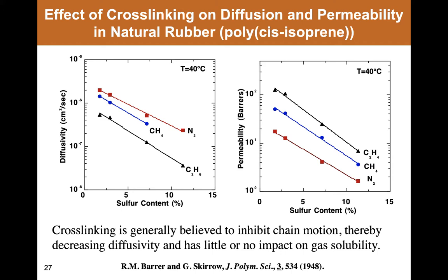And so what's being shown in this slide is the permeability of natural rubber as a function of the sulfur content. And as the sulfur content increases, permeability goes down. And what's implied by this is that the natural rubber would be blended with various amounts of sulfur and then heated for the sulfur to react with the double bonds that are remaining in the isoprene and cross-link the structure that way.